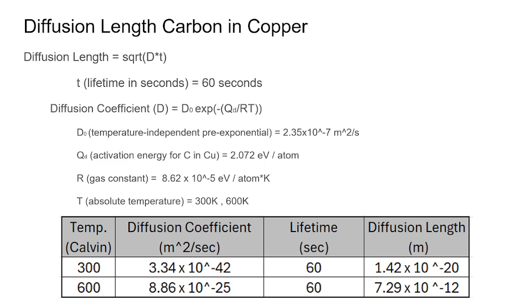And looking at the next row down, at a temperature of 600 Kelvin, the diffusion coefficient would be 8.86 times 10 to the negative 25 meters squared per second. Again, the lifetime would be 60 seconds. And plugging those into the diffusion length formula, you get an answer of 7.29 times 10 to the negative 12 meters.